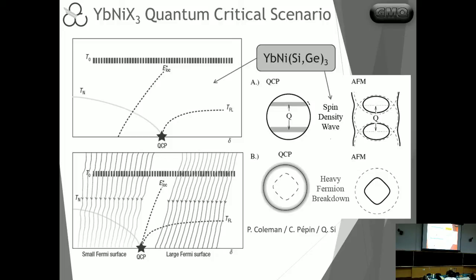In one of them, as we cross through here, basically we are just doing a reconstruction of the Fermi surface from this normal Fermi liquid state into a spin density wave here, right? So that, and only further on it's going to be localized away from the point. While in this case, we do have what they put forth as a collapse of the Fermi surface, where you have simultaneously a strong change of large Fermi surface to small Fermi surfaces as the 4f electrons leave the Fermi surface, right? And it just becomes a simple antiferromagnet there. So what we could say then in this case is that in our system, this is what's happening, right? In this ytterbium nickel silicon germanium system.